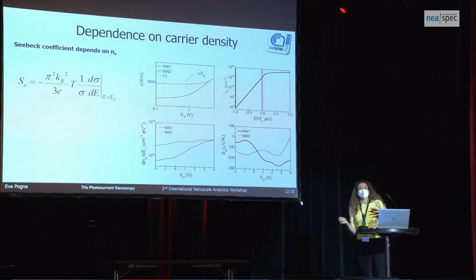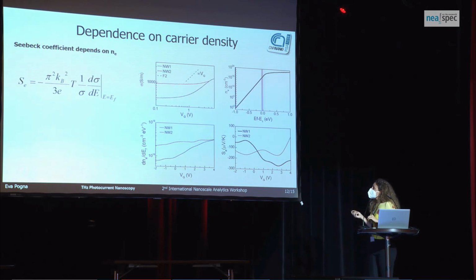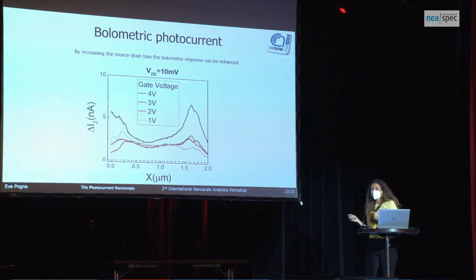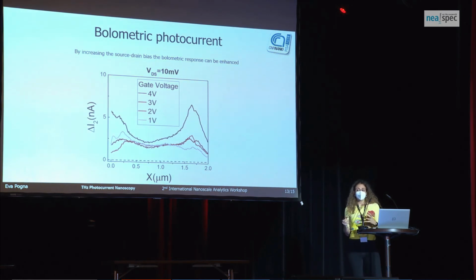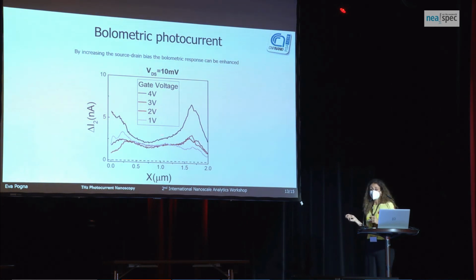The fact that this effect becomes dominating over the bolometric response at high carrier density is not so surprising, because of the correlation between the Seebeck coefficient and the carrier density. We can try to evaluate the Seebeck coefficient starting from the transconductance curve, so the current change with the voltage, and estimate the Seebeck coefficient. I'd like to say that the two mechanisms are present in a nanowire, in this type of material, and we can enhance the bolometric effect by increasing the current so that it becomes dominating even at high gate voltages, when we would expect to see the photothermoelectric effect.